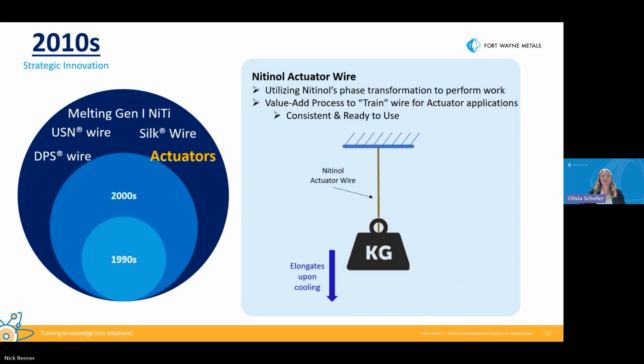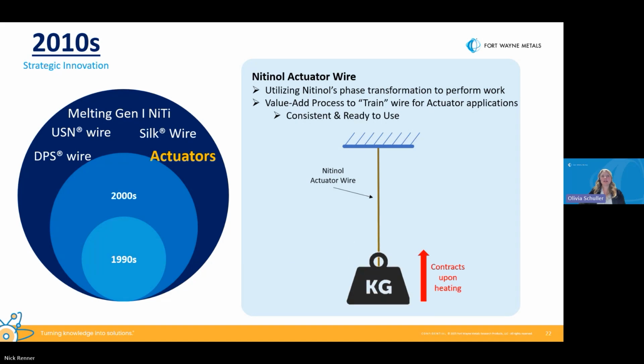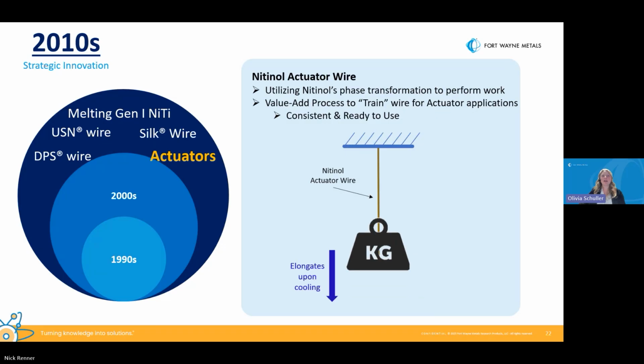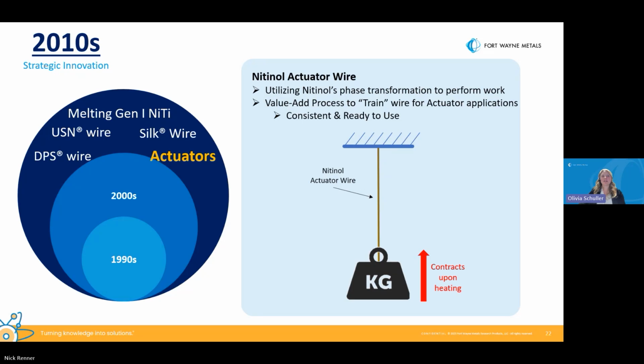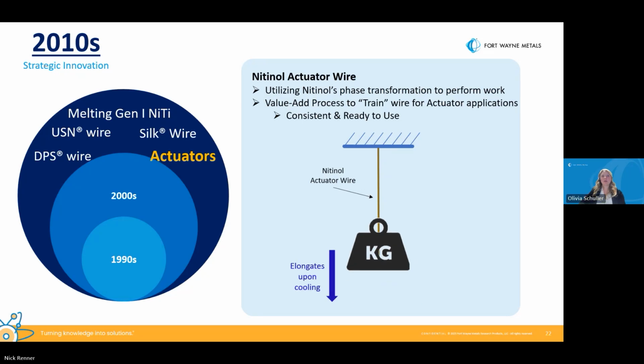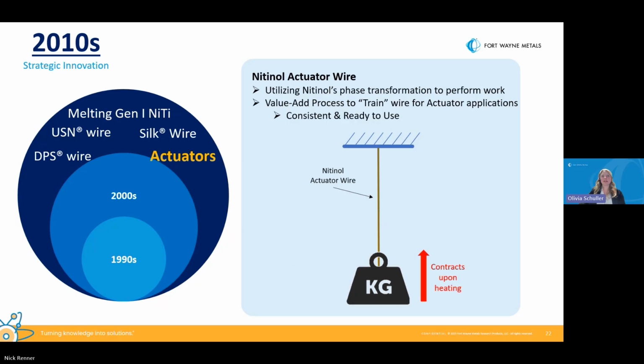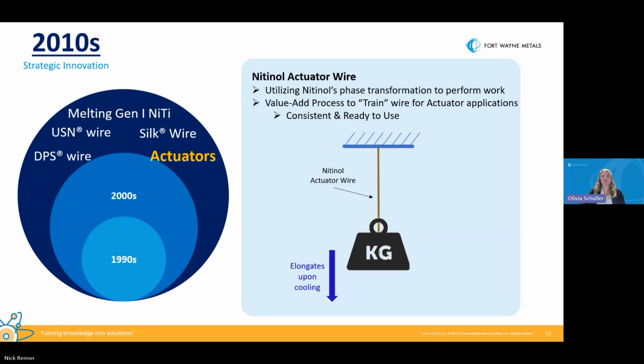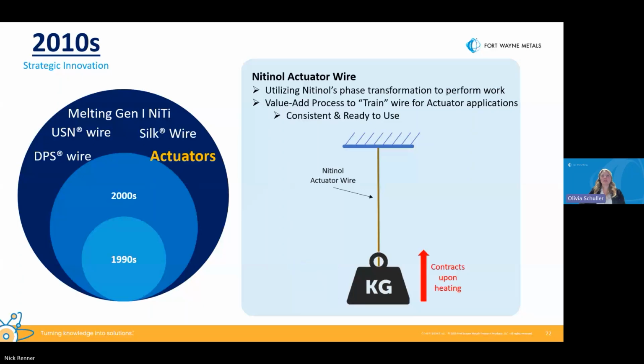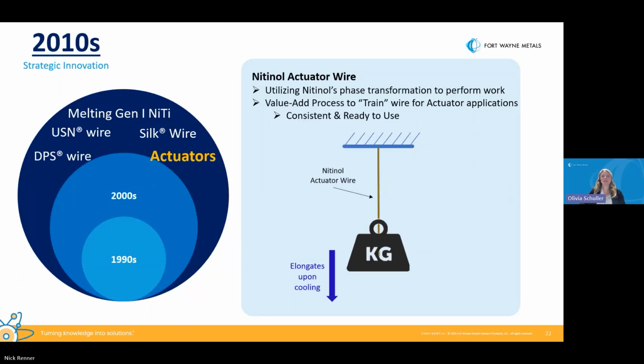The material is in the martensitic phase at room temperature, and then when exposed to a heat source, such as a heating element or current, the wire will heat up and transition to the austenitic phase, thereby contracting and doing work. When the heat source is removed, the wire will return to its martensitic phase and is ready to be elongated by a return force, such as a bias spring. This process can be seen in the graphic and can be repeated for millions of cycles.